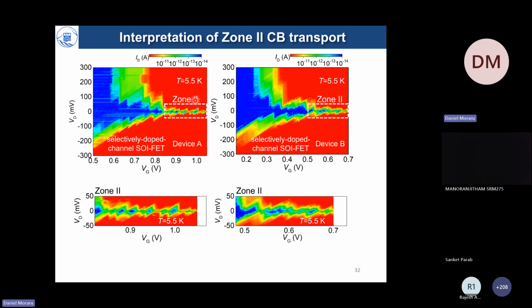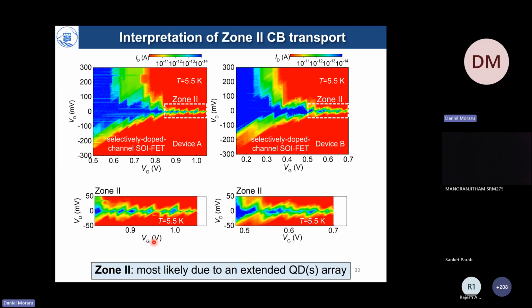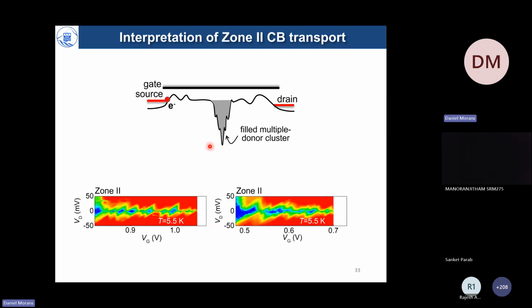About zone 2, the situation is much simpler. These Coulomb diamonds are, as shown in the zoom-in images on the bottom, closed diamonds. It's unfortunate that these are a little bit affected by noise, but they are still clearly sequentially observed diamonds, not perfectly periodic, and that means that we may have a quantum dot array working in this kind of situation. By that time, the gate voltage allows you to fill in this multiple donor cluster quantum dot almost completely, and we are left with only very shallow potential fluctuations, and electrons would tunnel in this way from source to drain at the higher voltages.